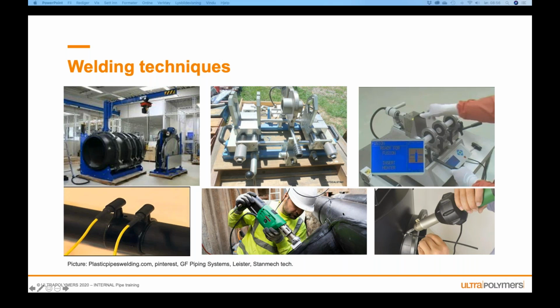And that is not so easy, because the polyethylene pipe material is much stronger than the polyethylene we are using in rotomolding. The MFR is much lower. So you cannot use the parameters that are set for pipe in rotomolding. There you need to find out what kind of parameters are working, and it's a lot of testing to see if your welds are good enough.